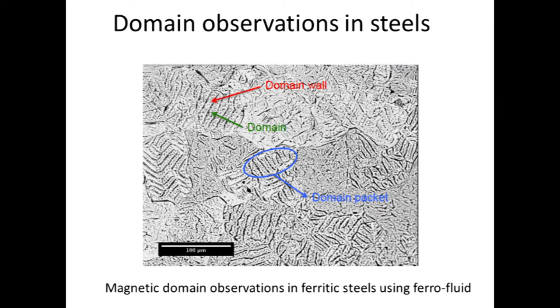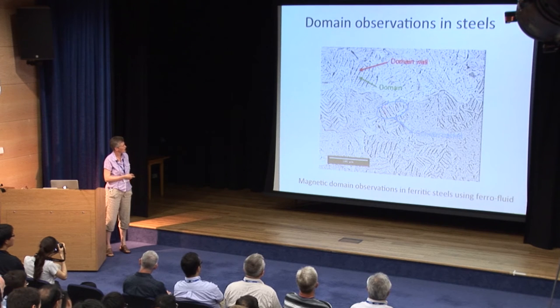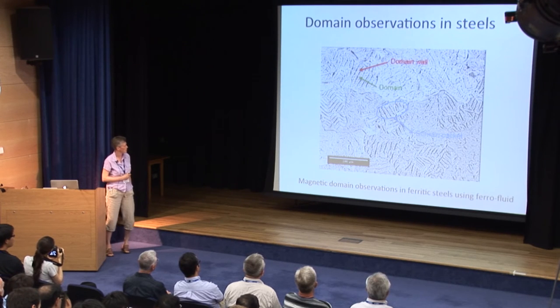In order to do that not just in theory, we need to be able to observe the interaction between microstructure and magnetic properties. Here's an example of what we mean by domains within steels. A lot of you may be familiar with this in magnets or electrical steels, but in engineering steels they are quite a bit more complex and domain structures are generally finer. Looking at these domain structures, we have packets with parallel domain walls, and you can see these packets of domains.